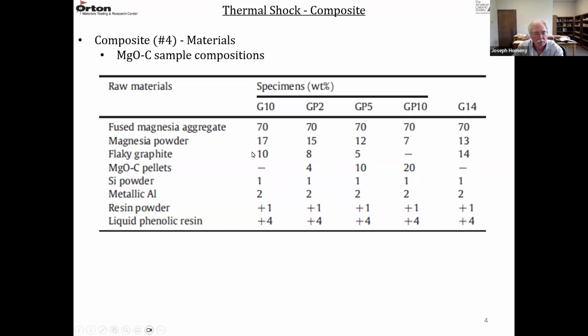So the combination of all these 3 was always 27%. So here they took out some of the magnesia powder, some of the flake graphite and added 4% of the MgOC pellets. And here, GP, that was GP2, GP5 had 10% of the pellets, GP10 had 20%, and G14 is basically duplicating a commercially available MgO carbon composite at 14 weight percent flake graphite. And this one had no level of the pellets, the MgO carbon pellets.